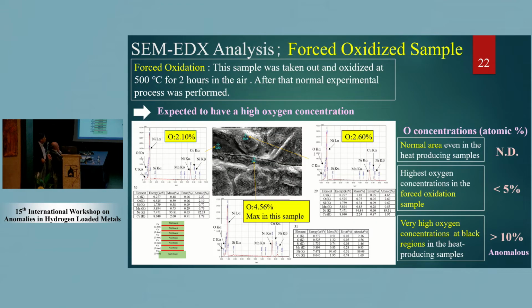And after that, we tried forced oxidation. This sample was taken out and oxidized at 500 degrees for 2 hours in air. So this sample was expected to have a very high oxygen concentration. But after the experiment, the maximum value in the forced oxidation sample is 4.56, lower than that of the heat-producing sample.